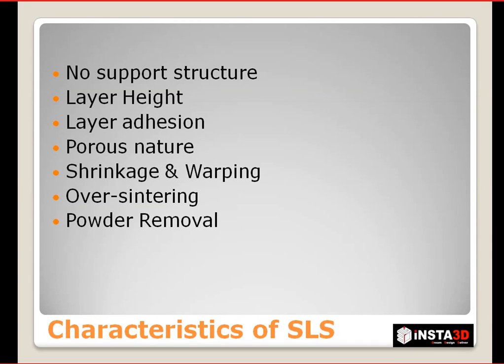In SLS technology, there are a few errors which happen, called shrinkage and warping. Warping is similar to the warping effect in FDM technology. It happens due to the internal stresses produced in the 3D printed part, whereas shrinkage happens due to the sintering of powder. And there is another disadvantage, which is called over sintering. Overexposure of laser light onto the powder with intricate details can lead to over sintering, and 3D printing holes will be difficult in SLS technology. For holes around 0.8 or 1 mm in diameter with a large wall thickness, the chances of over sintering are very high. The over sintered part will ruin your 3D print.